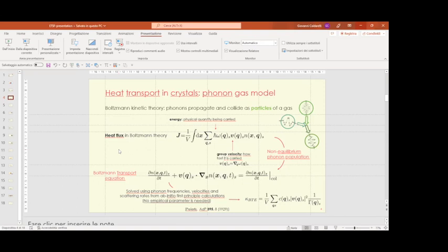Phonon scattering, and what about the isotopic effect? This is a kind of impurity that you have to introduce in there, and also if you take into account the electron-phonon coupling, which is also going to provide a self-energy effect on your phonon propagator. So do you take into account this electron-phonon coupling in your approach? No, we didn't take into account electron-phonon coupling because typically these kinds of systems are insulators, so they have a gap that is fairly wide, wider than the available phonon energy for electron scattering. So we don't take into account this kind of effect, considering that it is negligible.